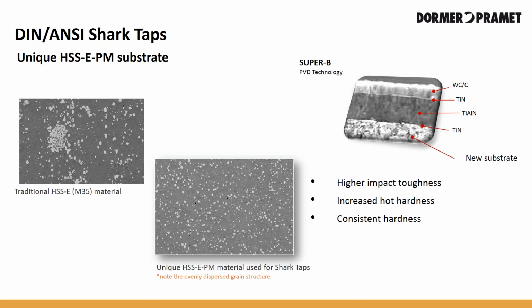Looking at the microstructure pictures on this slide, you can see that the carbides in the material used for our Shark taps are finer and distributed much more uniformly. This gives the new substrate a 30% higher impact toughness at the same hardening temperatures. This higher impact toughness is especially needed in threading applications. But the impact toughness is only one component of the cutting ability of the material. Another key component is the high hardness properties. Combining the new HSS EPM substrate with the coatings specified further enhances the performance of these products.